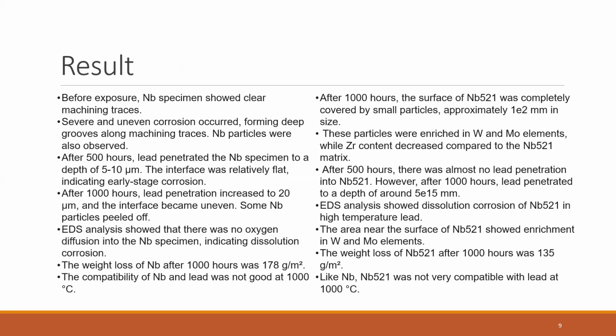Before exposure, niobium specimens showed clear machining traces, and uneven corrosion occurred, forming deep grooves along machining traces, and particles were also observed. After 500 hours, lead penetrated the niobium specimen to a depth of 5 to 10 micrometer. The interface was relatively flat, indicating early stage corrosion. After 1000 hours, penetration increased to 20 micrometer and the interface became uneven. Some of the niobium particles peeled off.